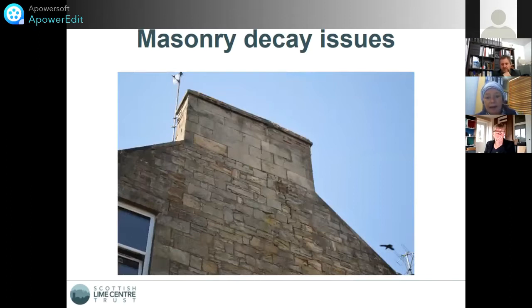And again, we've got issues. You'll very often see accelerated decay of masonry in line with chimney flues, because most of these chimney flues behind this masonry are not lined, and the sulfur from burning solid fuel fires, and particularly any cement overpointing that's been applied as a later repair, and uncontrolled access to water can lead to problems of sulfate attack, for example, where the mortar beds and joints expand and can cause masonry decay issues.